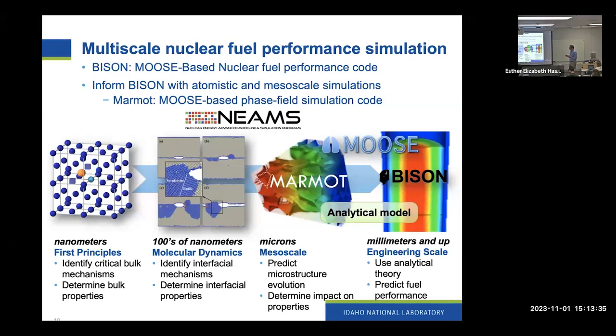So we inform Bison with a combination of atomistic and mesoscale methods. Often we'll use first principles techniques like density functional theory and molecular dynamics to calculate parameters at the atomistic level. Sometimes those are passed directly to Bison, but often we need to account for the microstructure of the fuel. So we use our mesoscale code MARMOT, which is basically the Moose phase field module with some additional materials and physics that are necessary for nuclear fuel performance. Then we develop some kind of model that can be used. Sometimes it's a single parameter, sometimes it's a model form that gets passed to Bison for use in engineering scale fuel performance simulation.